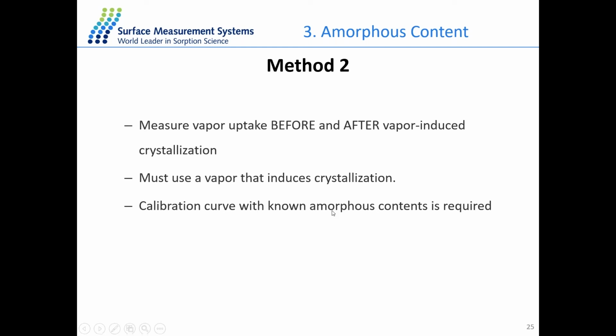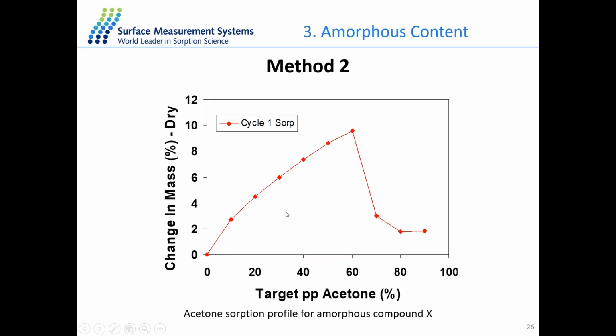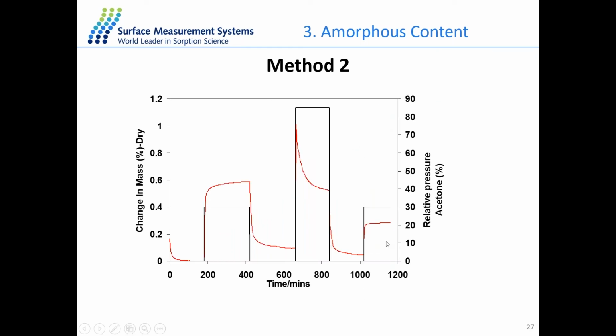And for this method, we first need to have a sample of interest that will be induced to crystallize by a vapor. So for example, for one of the samples we have, we perform acetone sorption on the sample, and at 60% RH, it will crystallize the material. There is a significant decrease in the mass. And when we set up the method, we just simply set different stages.